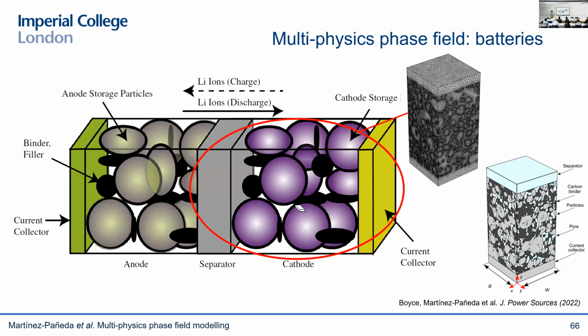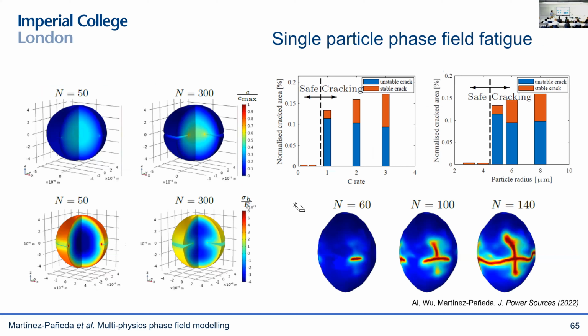Then we were able to deliver predictions as a function of the particle radius, the charging conditions, the particle geometry, the location of cracks, and so on and so forth. So again, we have a virtual tool that allows us to predict over realistic engineering timescales when cracks will initiate, when those particles will crack, and how this will affect battery performance. For example, we could determine what is the charging rate below which you don't see any cracking, or what is the particle size below which you don't see any cracking.